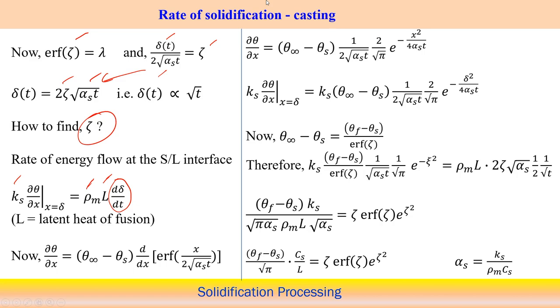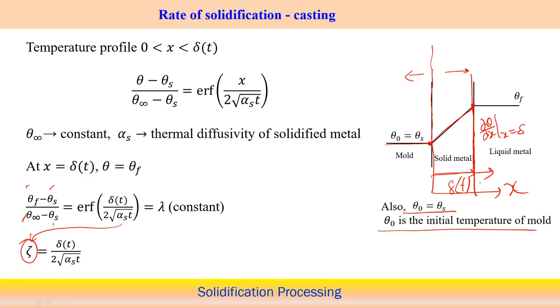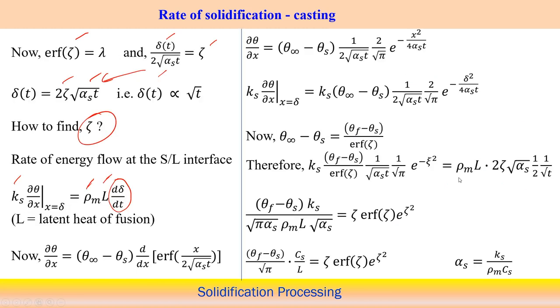Now, this is the energy flow at the solid-liquid interface that should be balanced here, because at this point the solidification front is moving continuously, changing the phase from liquid to solid. So that is why at this point the heat flux should be equal to the amount of heat released to change the phase from liquid to solid. So the energy balance should be maintained at the solid-liquid interface, and from there we are getting this kind of equation here.